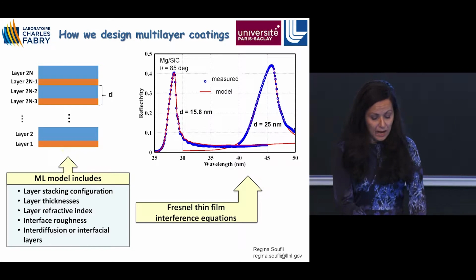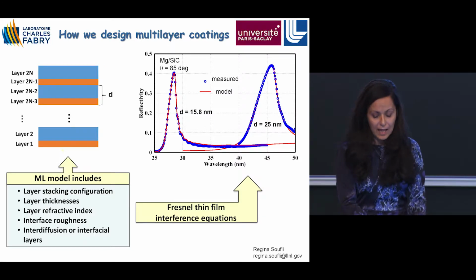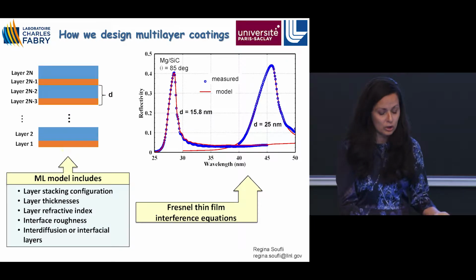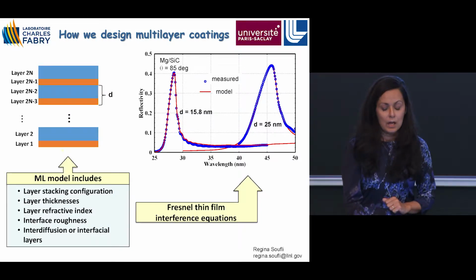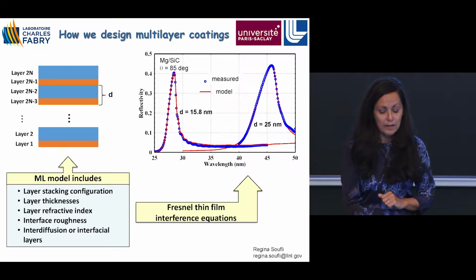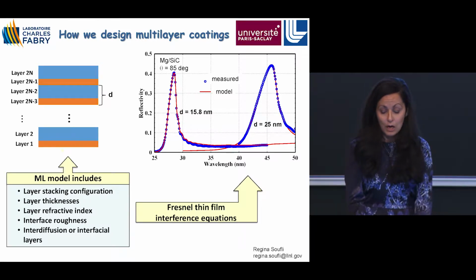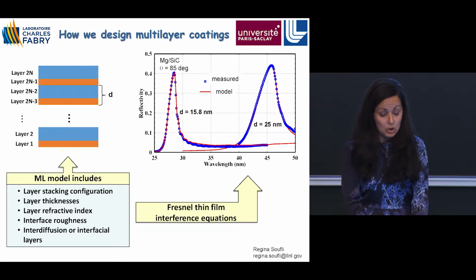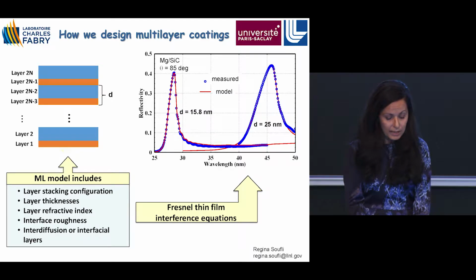So you feed these parameters in the Fresnel equations, and you develop a model, a design model for your coating. You deposit your coating, you measure it. I'm going to explain how you measure it in a moment. And then you adjust your model parameters so that you can have a beautiful fit of the data like we're showing here. So this sounds pretty straightforward, except we don't know an important set of parameters here.